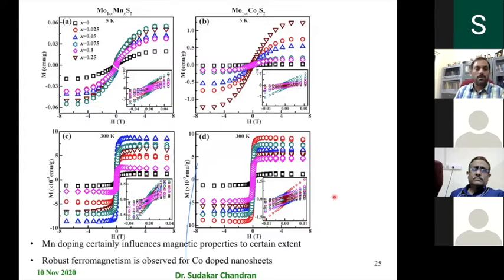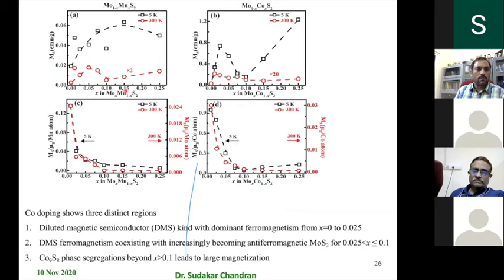10%, you happen to see in the XRD the Co9S8 phase, which is in fact magnetic in nature. So below that, obviously what you see is as you increase the doping concentration, the magnetization increases and comes down. In fact, the increase in the magnetization for the cobalt doping is almost 10 times more than manganese doping. You can appreciate this change from the saturation magnetization shown at both 5 Kelvin and 300 Kelvin in these plots.